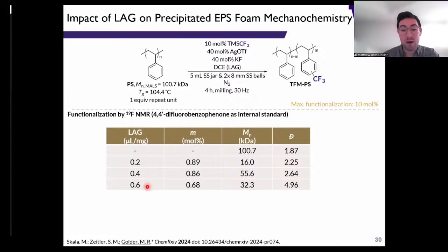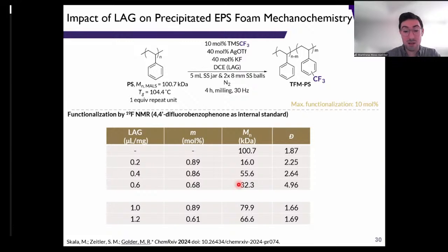So this small amount of LAG solvent, up to about 0.6 microliters per mg of substrate, is not quite enough to really quell that chain scission. And on the other end, we actually start to see a little bit less chain scission as we get up to about 1 to 1.2 microliters per mg. But we start to shut down the productive reaction as well as we start to add too much LAG solvent.